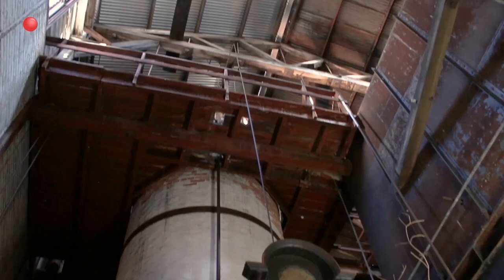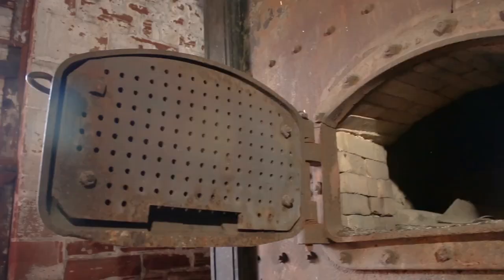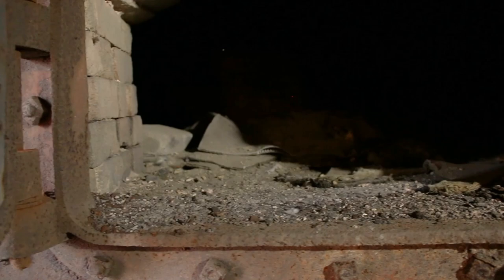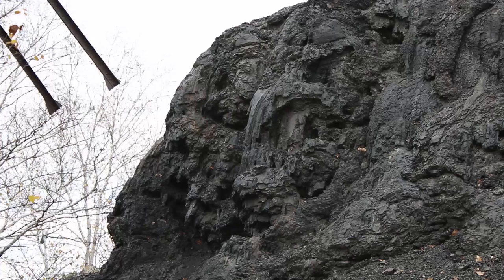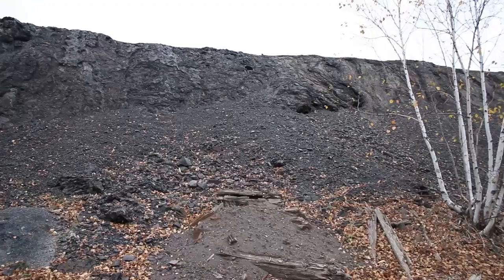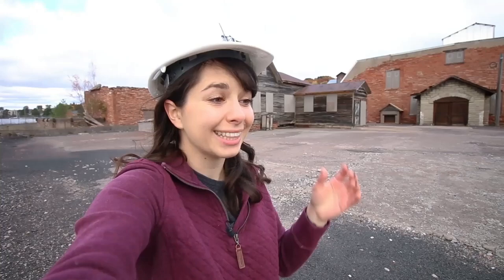This process was efficient, but some copper still ended up in the slag created in the furnaces. The Quincy Mining Company was not going to let that copper go to waste — there is a whole building dedicated to getting it out, called the Cupola Building. Here, a vertical furnace used direct heat rather than reverberatory heat. Coal, slag, and a bit of limestone were all loaded into the top of the furnace. The slag melted, and that last bit of copper drifted down to the bottom where it could be tapped out. The remaining molten slag was then taken outside, and there are some significant solidified slag piles on site.